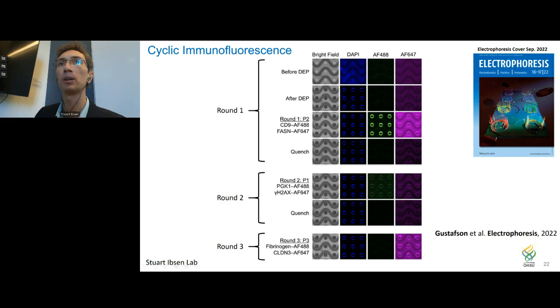And then we go through a quenching step that basically kills the fluorescence, but is done in such a way as to preserve the biomarkers for another round of staining. So we can come in with a second round of staining for these different biomarkers here, and we can see that we get staining of them again, even after the first round had been bleached. And that allows us to quench these again. And then we can come in with a third round of biomarkers and see that these particular exosomes are positive for claudin-3. So this is a really powerful technique that allows us to look at multiple biomarkers in the same sample on the same chip without having to recollect another set of exosomes from the same patient.